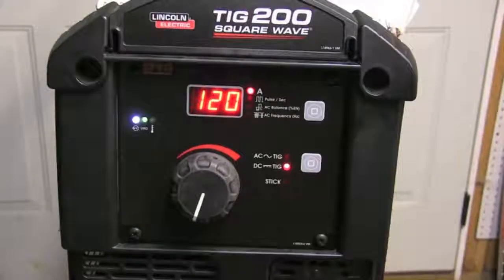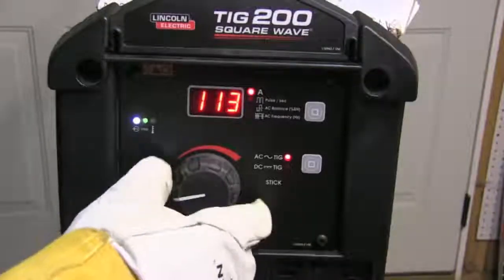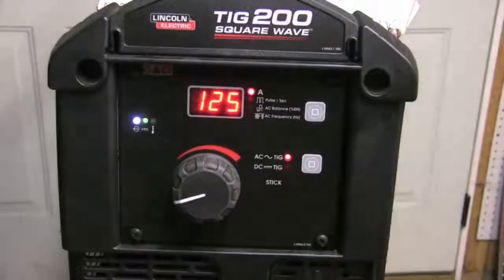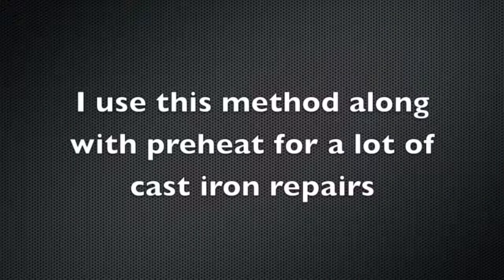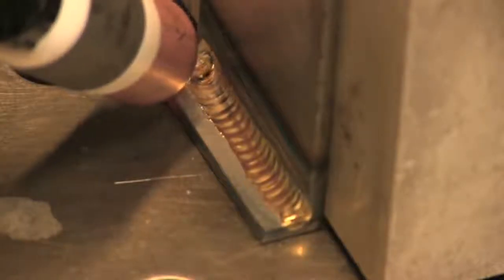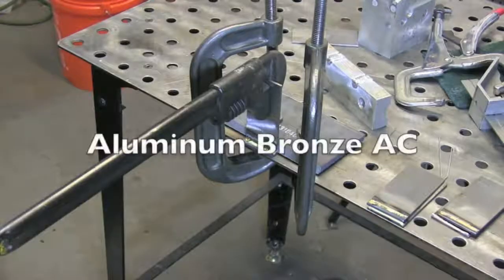Now the thing about this is you can use any machine basically, but if you have an inverter, you can set the AC balance for a very high percentage of electrode negative or very little cleaning. And it's almost like welding on DC. You can pinpoint the heat a lot. I use this method along with a preheat for a lot of general cast iron repairs. You can see how that cleaning action, the etching area, just kind of cleans the path for the braze metal to flow, just same as it does on aluminum. It also keeps the filler metal really clean. The filler metal does have aluminum in it, keeping it from scumming up. And I just had a lot of success using this method, alternating current, same settings I would do on aluminum almost.